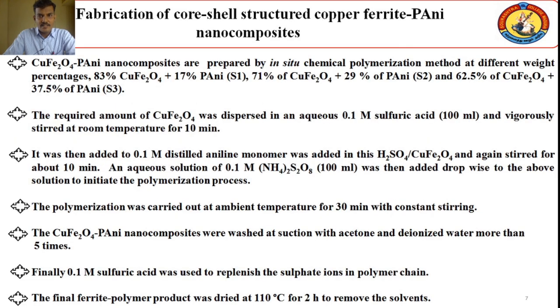To fabricate the core shell structured copper ferrite polyaniline nanocomposites, here we are taking three different compositions. One is 83% of copper ferrite added with 17% of polyaniline, then 71% of copper ferrite added with 29 weight percentage of polyaniline, and 62.5% of copper ferrite added with 37.5% of polyaniline. So three important compositions have been maintained, mentioned as S1, S2 and S3 respectively. To synthesize the polymer material of core shell composites, here we adopted the in situ polymerization technique.